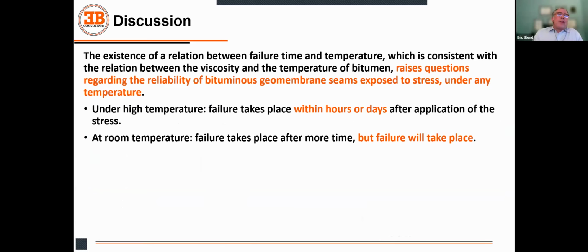So in terms of what can we get out of this? The existence of a relation with the failure time, from an engineering perspective as a geotechnical engineer, it raises questions regarding the reliability of bituminous membrane when they are exposed to stress under any temperature, because we can see that there is a relation between the temperature and the failure time, but viscosity goes down to much lower temperature. So if there is a failure, it's going to be within hours or days.